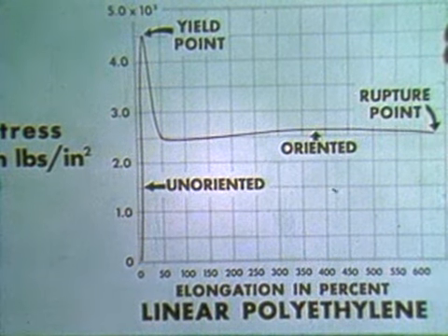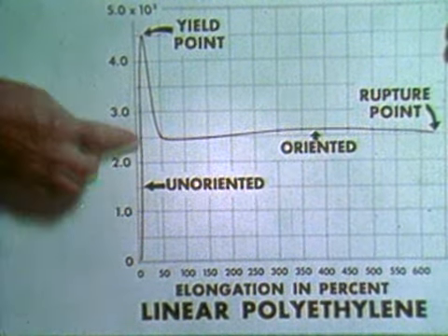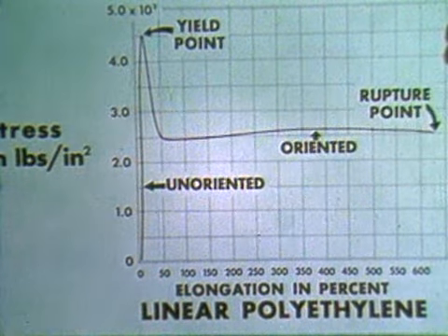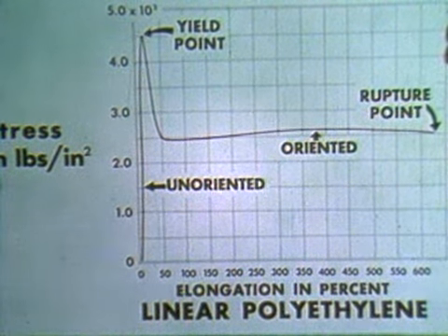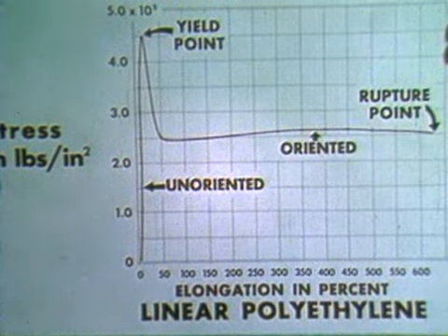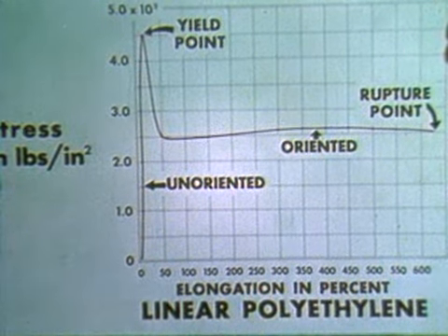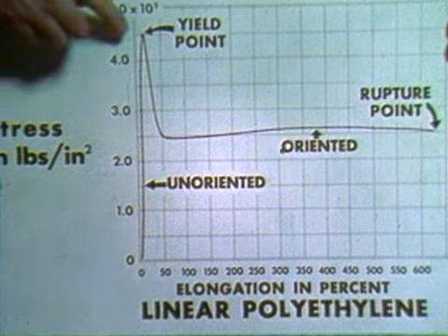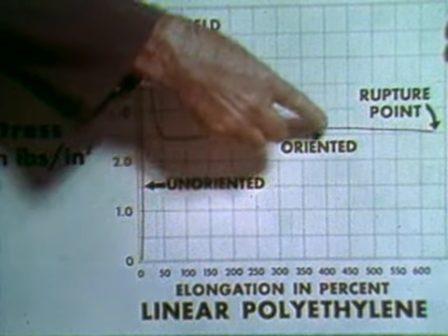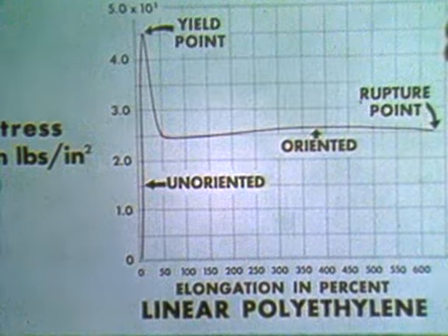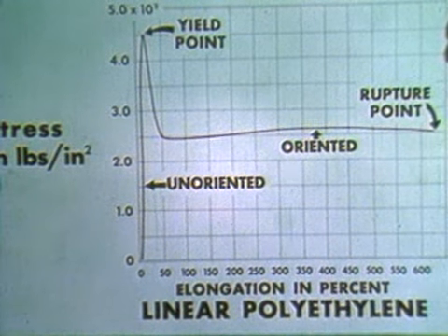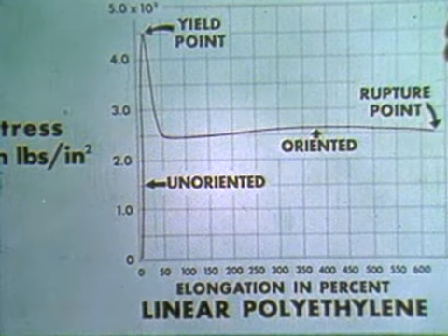At first, the sample resists elongation. X-ray studies show that initially, the crystals do not face in any particular way. They are unoriented. Then, at a critical stress, the sample yields and flows. Molecules straighten out and are rearranged.